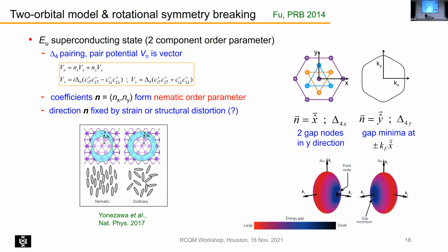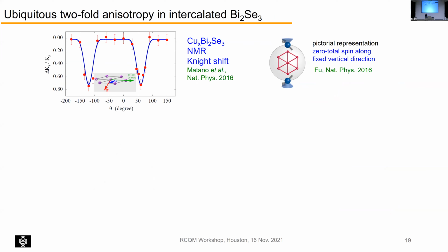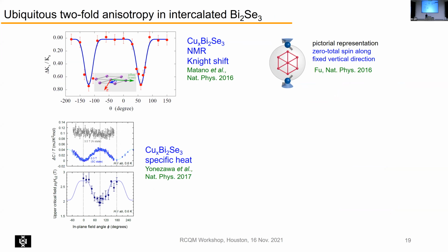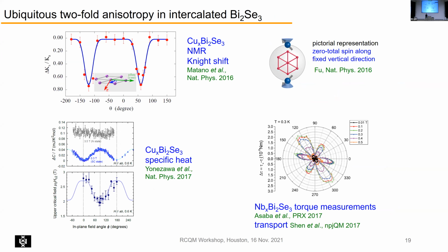Now this is about the strontium doped case, but in fact, very similar phenomena have been reported for the copper doped case from NMR. I have not time to go into details here. Also 2-fold anisotropy. So here you directly measure the Cooper pair spin moment. Also in the specific heat of this material, and also in the upper critical field. And also for the niobium case from torque measurements, there is evidence for a 2-fold symmetry.